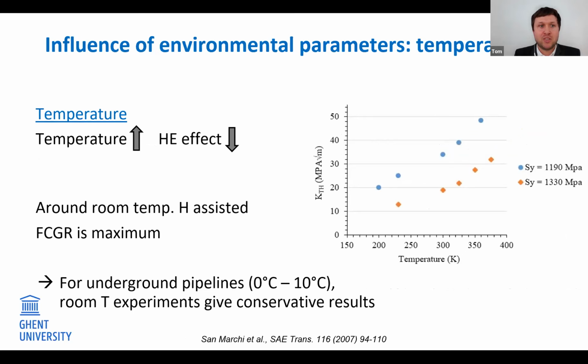The second parameter is the temperature. Carbon and low alloy steels exhibit less severe hydrogen embrittlement as temperature increases. The fatigue crack growth rate was found to be maximum at room temperature. The influence of temperature can be explained based on the hydrogen trapping model, in which hydrogen is considered to diffuse through the material or be trapped with a certain binding energy at these microstructural defects and constituents.